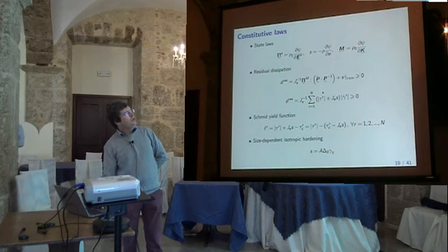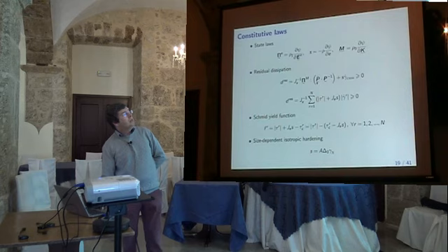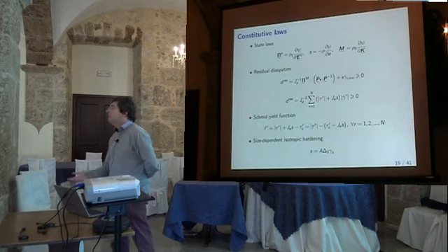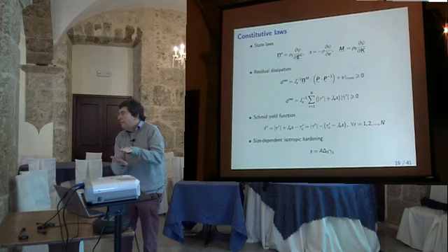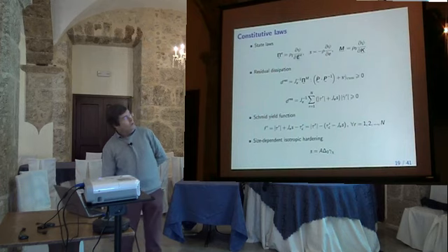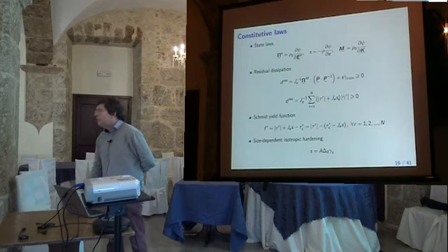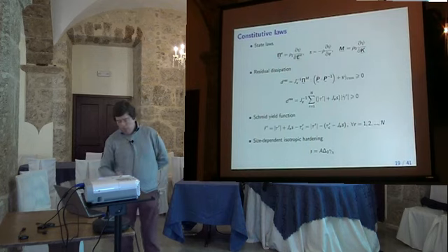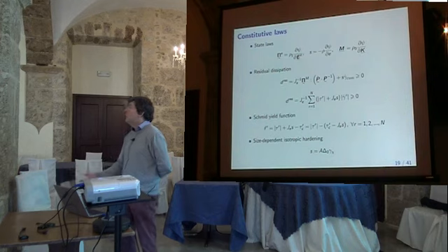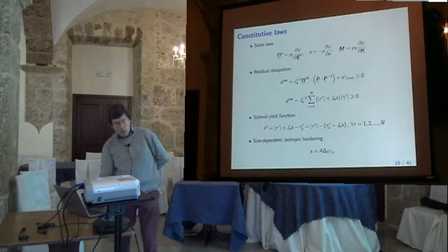Okay, so now we look at the dissipation of energy. Here it is due to slip. Look here, the slip rate. And we have this quantity, tau, which is the projection of the stress, the Mandel stress, on the slip system. So this is the resolved shear stress in crystal plasticity, so the driving force for slip, here. And we have this additional term, this additional stress, this microstress I mentioned, which in fact will introduce some isotropic hardening due to gradient. How?